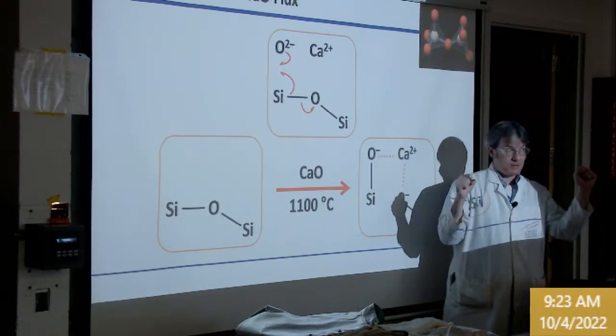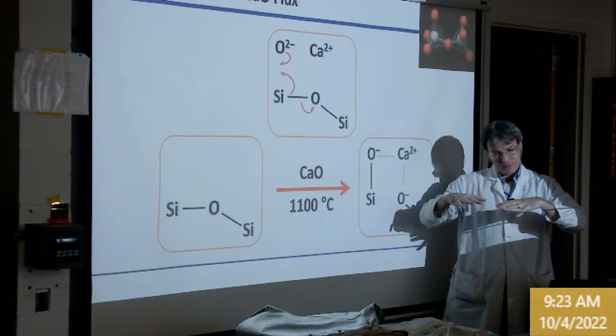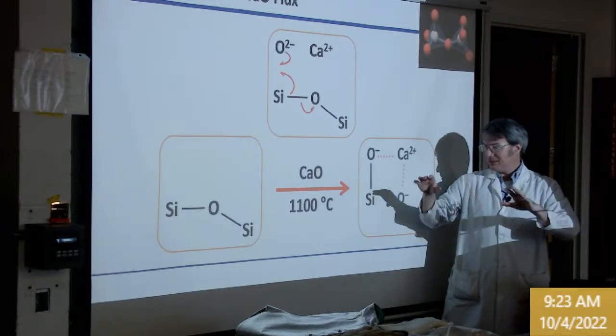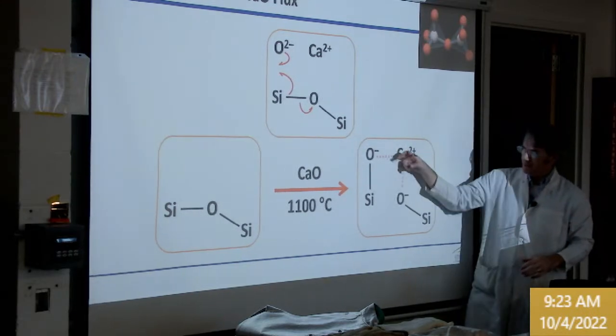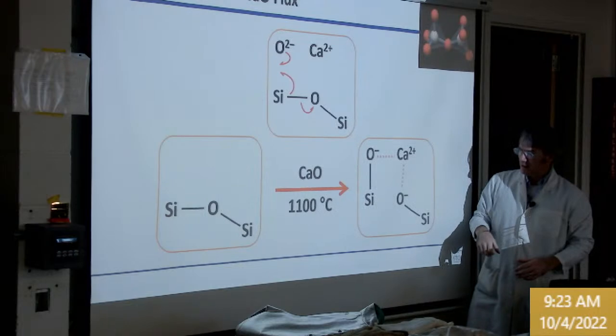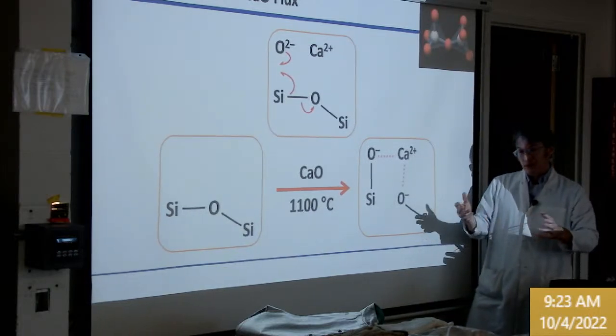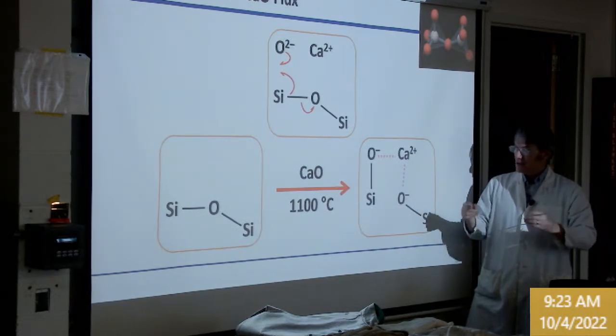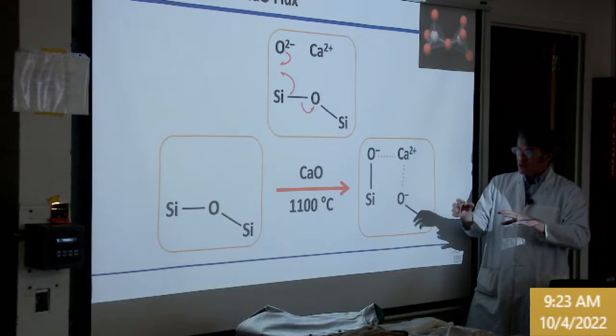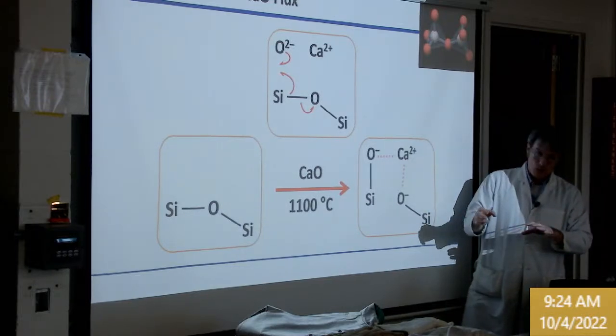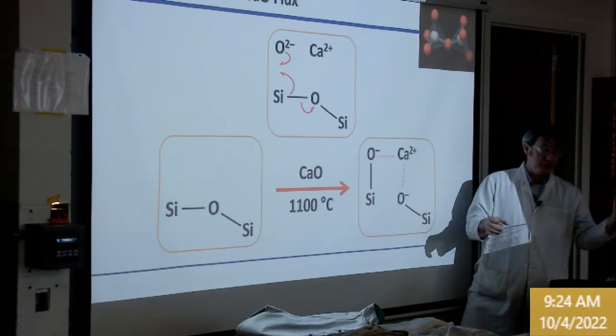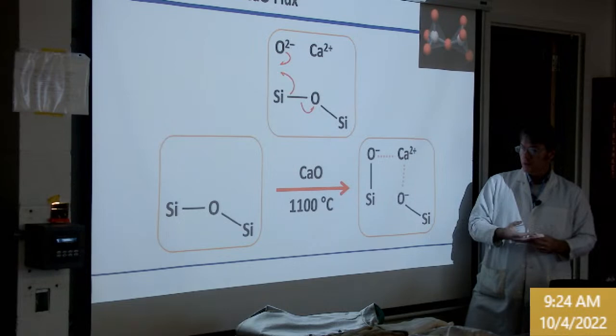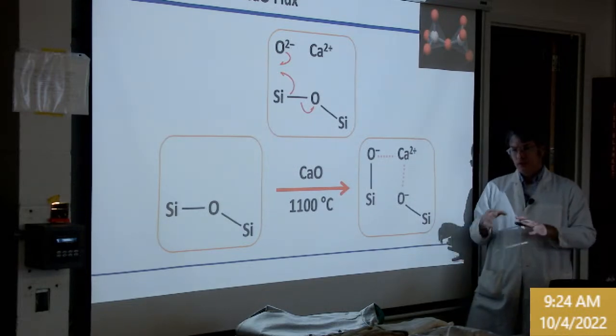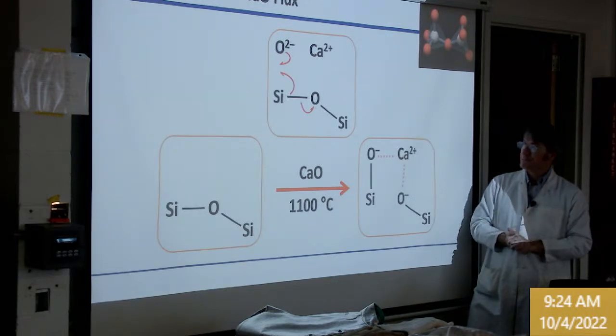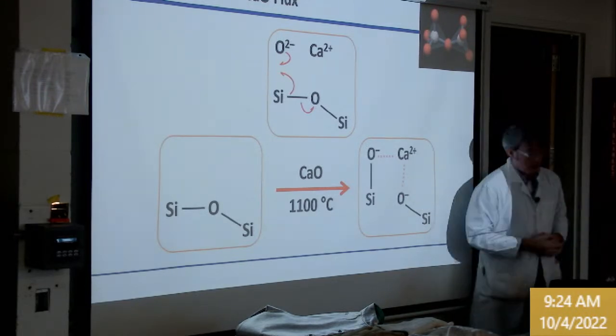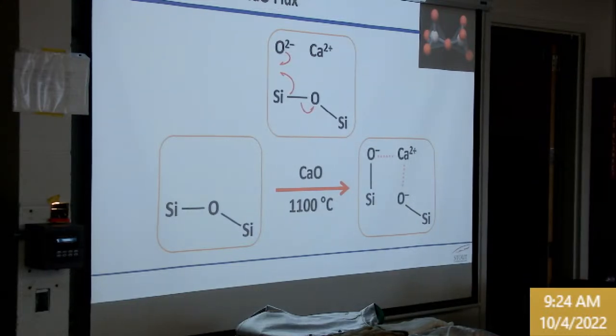This is actually a dynamic process where bonds are broken and reformed as the glass melts and flows. But the calcium still dwells some of the time linking two pendant oxides, which has a stabilizing effect. It still fluxes it, it still messes up the bond, it still turns it into a glass, but it also stabilizes it and makes the glass a bit stronger, a bit more resistant to attack by water. Some glass, if it's too highly fluxed, will spot and actually get cloudy over time. Calcium and even aluminum can help arrest that process, slow it down. So we've disrupted the bonds with ionic impurities, a flux and a flux stabilizer.